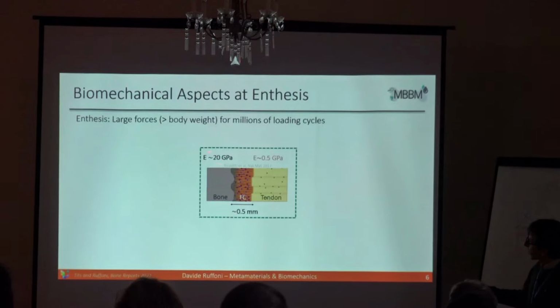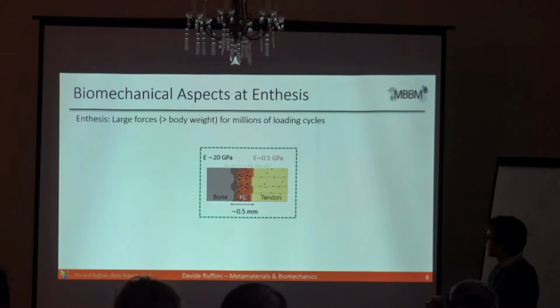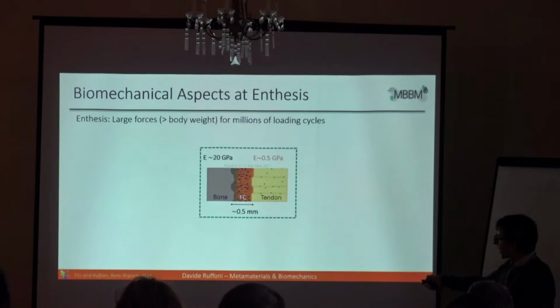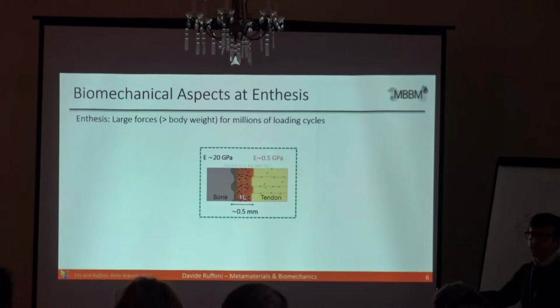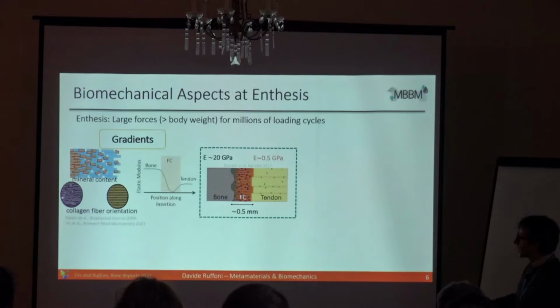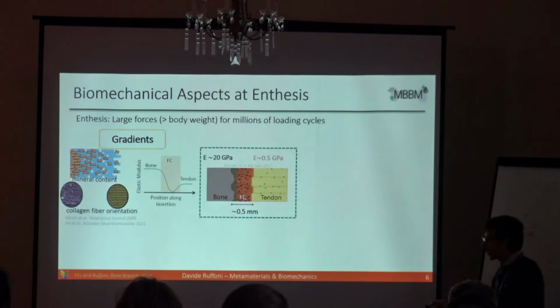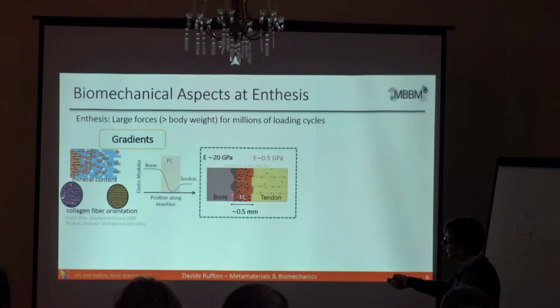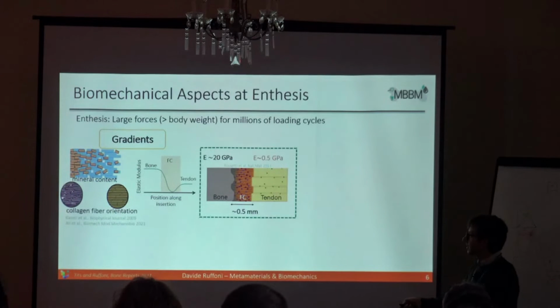Well, bone has a Young's modulus of about 20 gigapascal, tendon, let's say 0.5 gigapascal, and they are connected over a length scale of about 500 micrometers. And this is quite amazing because this region here supports large forces that can be higher than body weight for millions of loading cycles. Of course, we are not the first ones to investigate this. Many people have already looked at this. And there are several construction strategies that nature is putting in place.